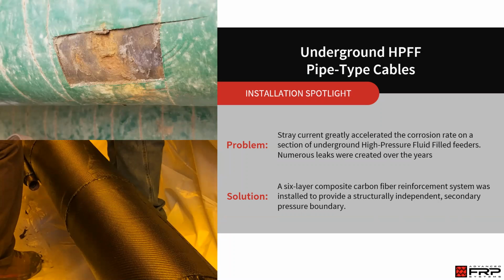So the first thing we ran into, an underground high pressure fluid filled pipe type cable that had stray current in that area that was greatly accelerating the corrosion rate. This complicated our repair in two ways. One, there were dozens of pre-installed barrels or externally welded repairs. So it wasn't a straight pipe anymore. And two, we had to look at how that stray current was going to affect the carbon fiber composite.